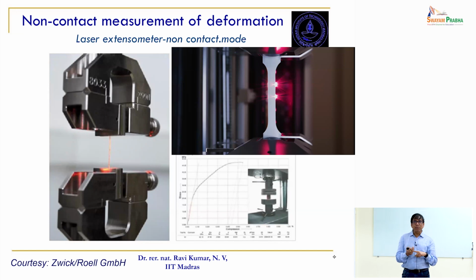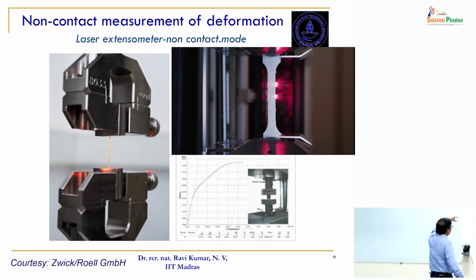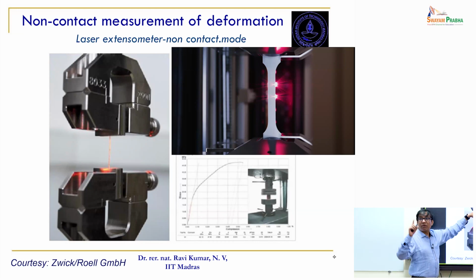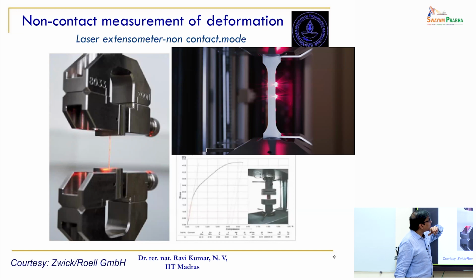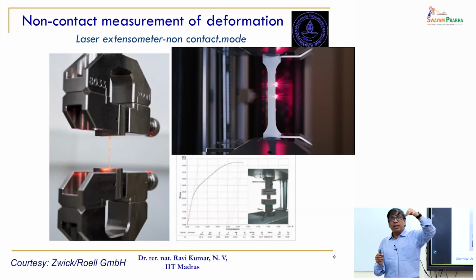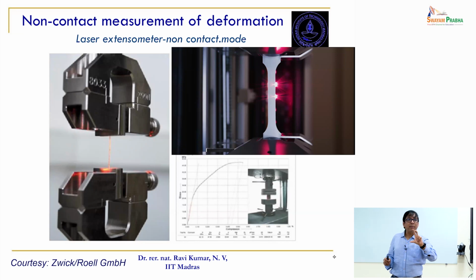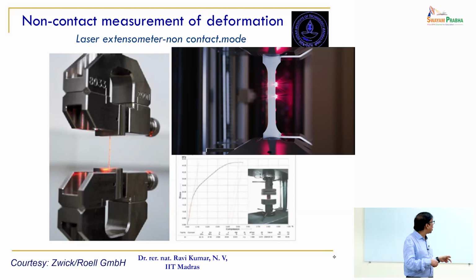So when you're dealing with extremely brittle materials, glass, ceramic fibers and so on, you have to know how to fix these samples. It becomes so critical, which many of them think is a very trivial thing. What is there in that? No, it's not so easy when you're dealing with ceramics and glass samples, and particularly when you're dealing with fibers. It's not a problem with metallic wires, but definitely a problem with ceramic fibers. So if you are able to fix it well and measure the strain very well, and ceramics do show very limited strain, but you should be able to measure such kind of strain, then fantastic. And it is a laser extensometer which is now used.